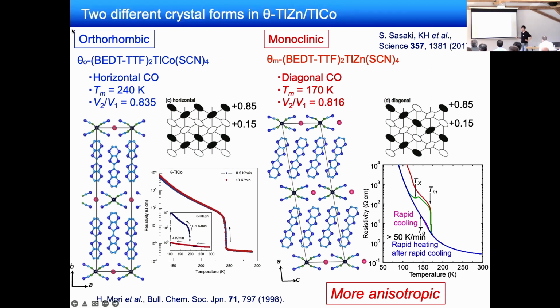And because the anisotropy of the triangular lattice is large, you need a very rapid cooling rate to make charge glass states. In sharp contrast, the monoclinic thallium zinc compound shows a diagonal charge ordering at 170 Kelvin here. And although the anisotropy of the triangular lattice of this material is larger than that of the orthorhombic one, you can actually see the large difference. The resistivity is very sensitive to the cooling rate, and you can make charge glass states by rapid cooling higher than 50 Kelvin per minute.